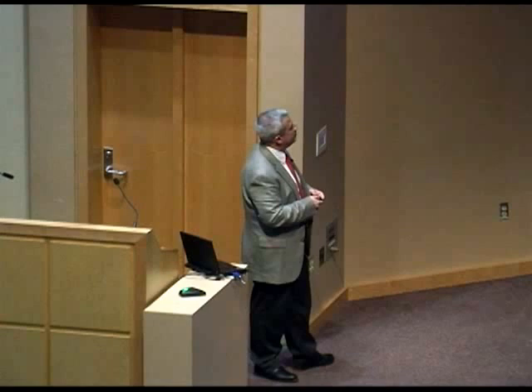I just go through this in collaboration with Jun Shu and Tom Maluk. So basically, Tom grows the crystals from chemical vapor transport just by exfoliating this tungsten disulfide. They also found just by exfoliating the tungsten disulfide, you find also this luminescence, this very sharp luminescence PL peak. And we find the 2LA mode, which only happens for a single layer. So we confirm that our CVD and this exfoliated one sort of work in the same direction.